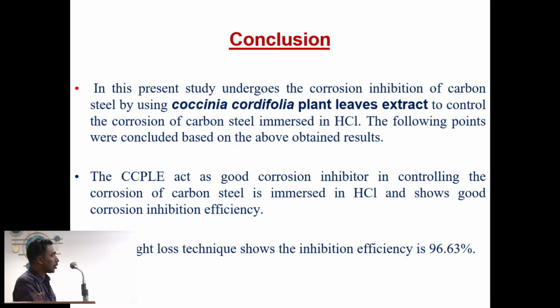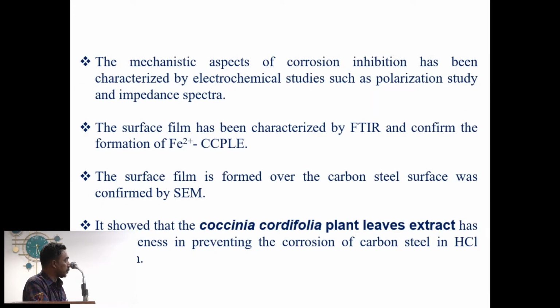The present study undertakes the corrosion inhibition of carbon steel by using Coccinia cordifolia plant leaves extract to control the corrosion of carbon steel immersed in hydrochloric acid. The following points were concluded based on the above obtained results. The Coccinia cordifolia plant leaves act as a good corrosion inhibitor in controlling the corrosion of carbon steel immersed in hydrochloric acid and show good corrosion inhibition efficiency. The weight loss technique shows the inhibition efficiency is 96.63%.